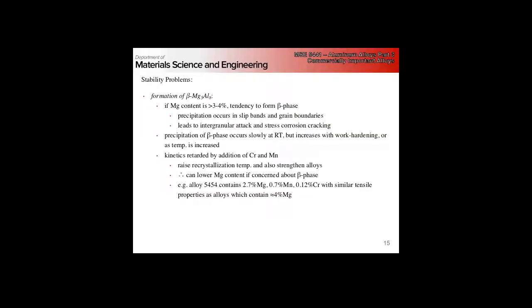The critical issue is the formation of the beta phase, which nucleates heterogeneously, typically on grain boundaries and slip bands, and this causes a huge problem for stress corrosion cracking.